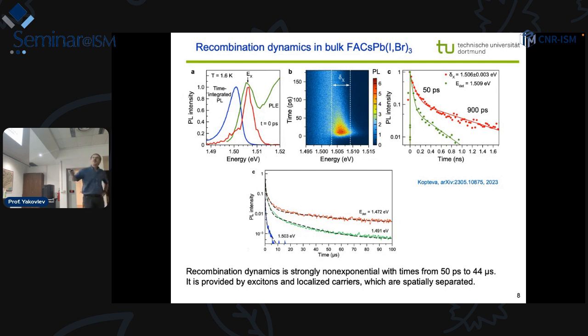So it's a black perovskite. And this is the low temperature spectra. The green line is absorption, nice exciton resonance we see here. If we make a CW photoluminescence, so continuous wave, then the line will be the blue one. So it has a 5 millielectron-volt Stokes shift from the exciton resonance.